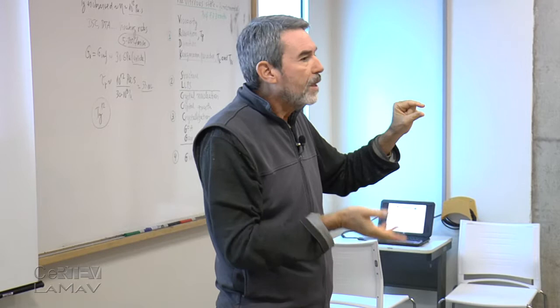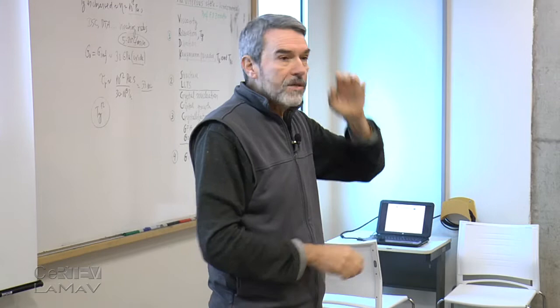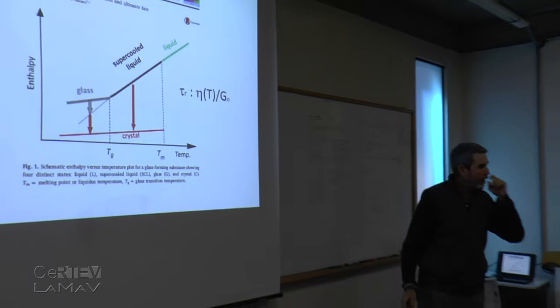There is no way to get heat out of the interior. So we had to change the composition. Our strategy is to add some elements that decrease the crystal growth rate of those crystals by increasing the viscosity. See viscosity again. We have chosen two particular oxides that increase the viscosity.